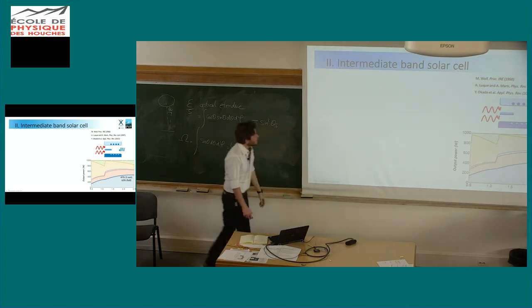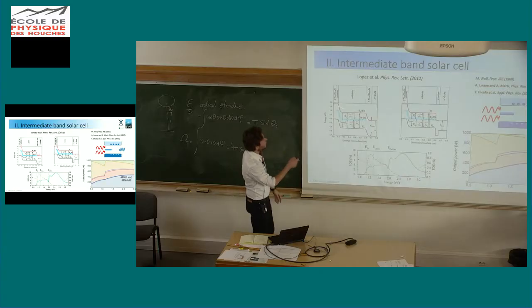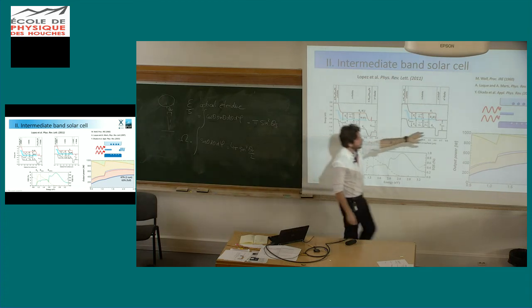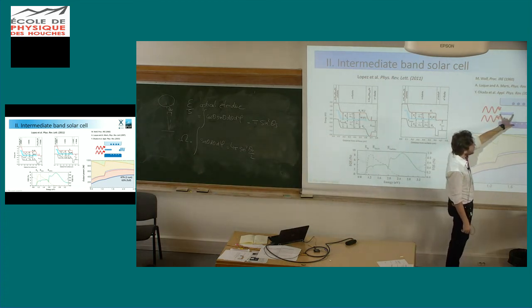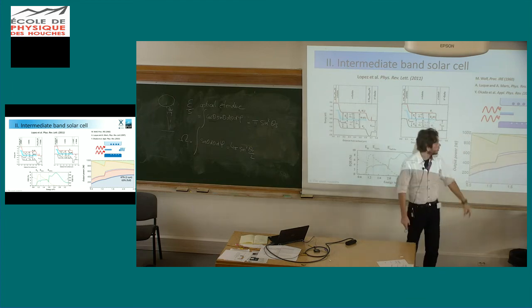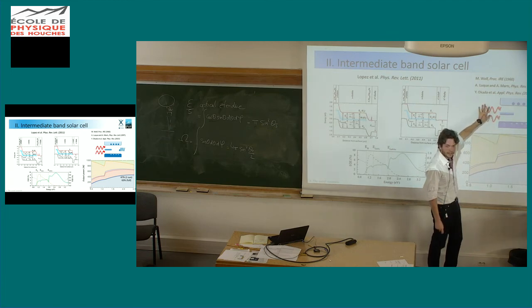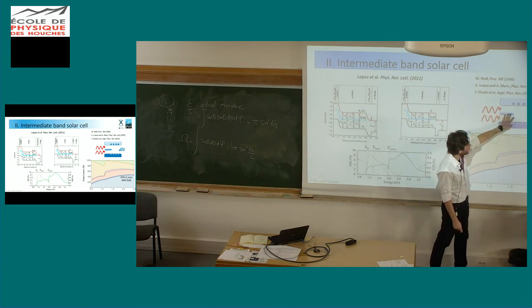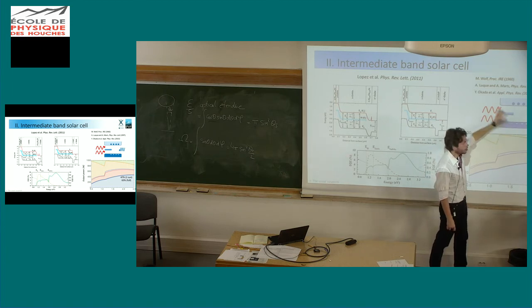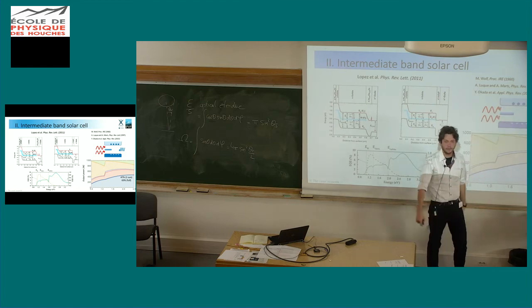And there is this quite beautiful paper with the III-V nanostructures. One of the key issues on these systems is to make sure that this intermediate band is well disconnected from the surrounding lattice, because otherwise you would absorb carriers here and they would be extracted, which means that on the other side you can inject carriers here and they will recombine. So if this thing here is connected to the outer world, what is really happening is that you have just killed the gap of the material.